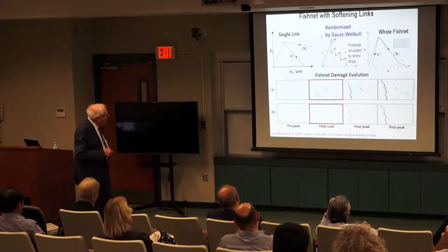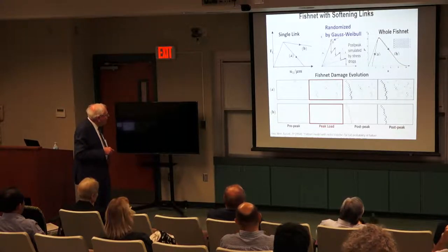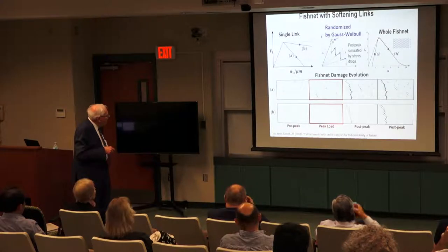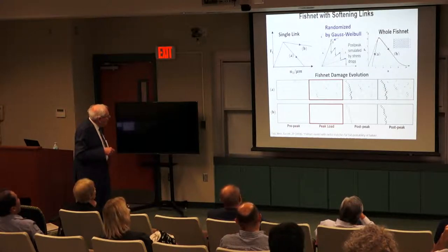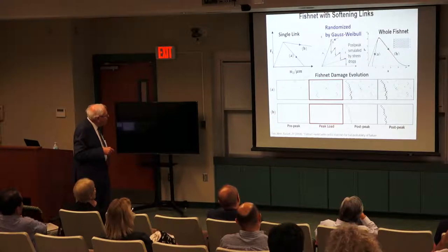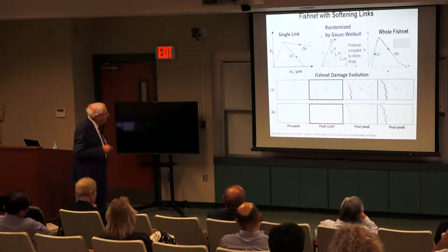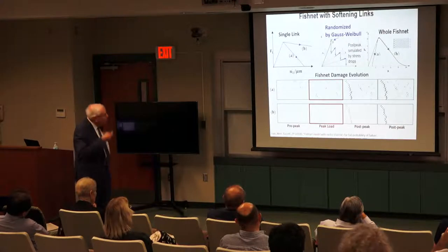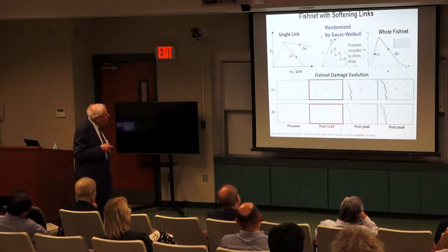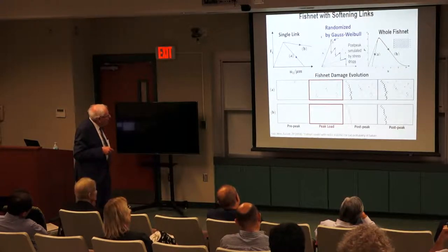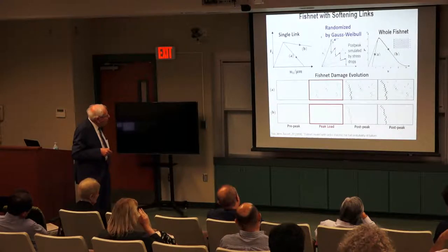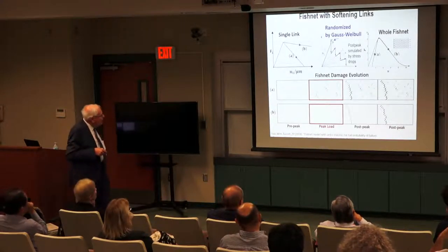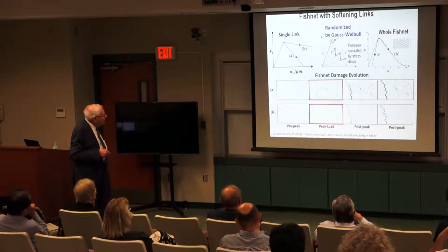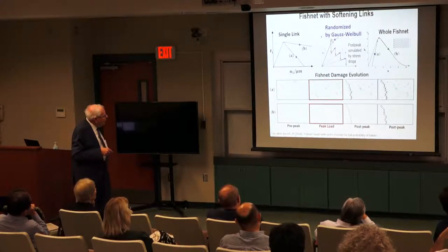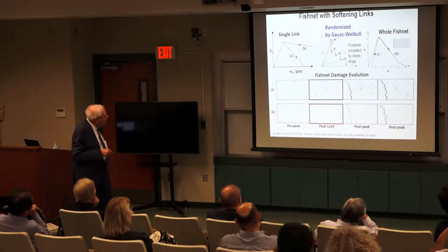in one link is not straight down or nearly straight down, which is perfectly brittle, but gradual softening. And that can be on various slopes. Eventually it can go to zero slope, which will be a plastic link. All right, so one needs a somewhat different approach. This previous analysis would not quite hold. So what do we do? We assume the link goes down, but it goes down in a series of jumps. And that greatly simplifies the analysis. Typically maybe 20 jumps. So jump down, you can reload, get to this curve, it becomes dynamic and so forth.